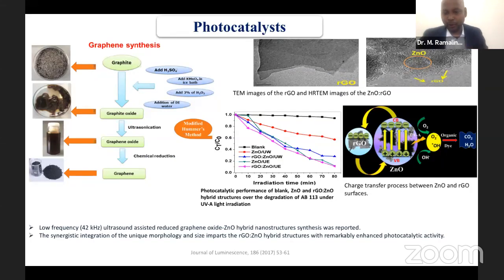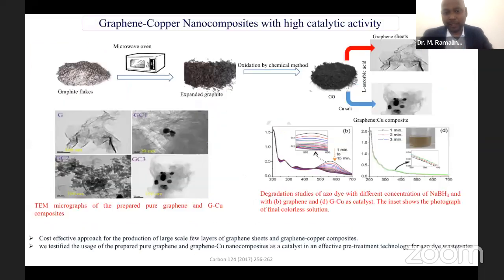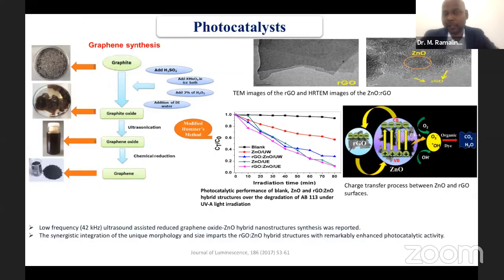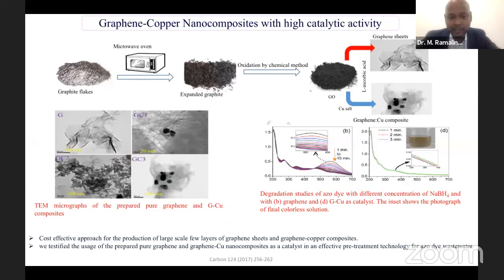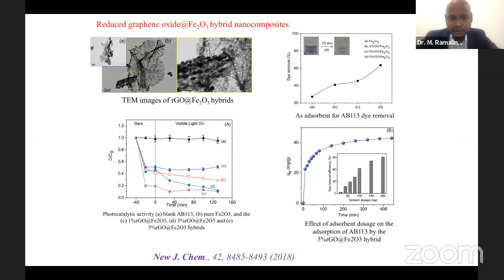But I want to show some results, more importantly, that we developed with graphene, because the current trend is to work more on graphene and reduced graphene oxide materials. We also utilize the opportunity to work on graphene based material for photocatalysis and wastewater treatment, especially wastewater treatment filter fabrication. This is reduced graphene oxide with iron oxide as a hybrid composite.